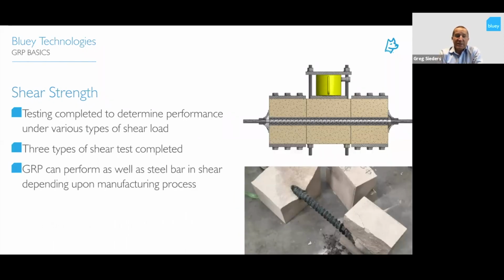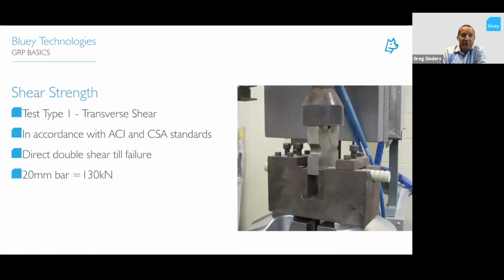Shear testing. There's a lot of shear testing that we performed on our bars to justify the performance of the product, so that's equivalent to steel or greater than steel. I'll carry you through those tests now. The first one was the transverse shear traditional testing in accordance with the ACI and CSA standards, direct double shear to failure. You can see there, a 20mm bar has 130 kilonewtons. The 25, what we talked about, has 170 kilonewtons in this testing.